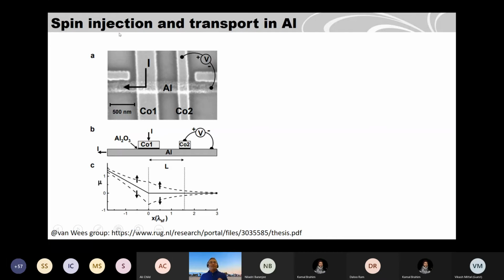So, spin injection and transport in aluminum. What people have done is that you have an aluminum electrode here, then you have ferromagnets. So you apply a current here, so that you inject spins at this point. So spin will go in both directions. This is the cross-sectional view. So spins are going in both directions. So you have a tunnel barrier to decouple the ferromagnet from the aluminum, so that you don't have any proximity effects or any kind of conductivity mismatch here, because spin again can go back to cobalt. So once you inject spin, you create a chemical potential difference between up and down spin at the interface in aluminum.